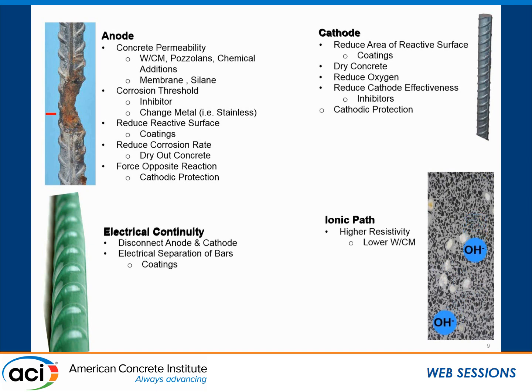The ionic path, we can change the resistivity of the concrete. This is ions moving through the concrete, supplemental cementitious materials, drying the concrete out. When you think about it, all the deterioration mechanisms in concrete, once I've got the concrete properly cured, if I can keep the water out of concrete, a lot of really good things happen. I don't have alkali aggregate reaction. I don't have sulfate attack. I don't have ingress of chlorides. I don't have corrosion.